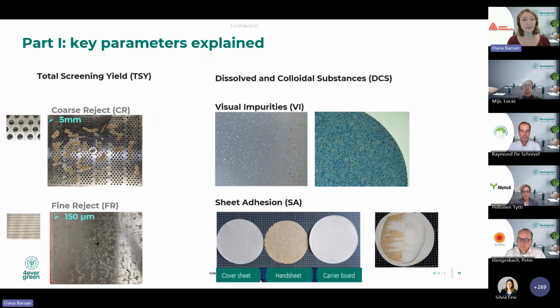And then there's a separate step called fine screening, where the smaller particles are separated, like fiber agglomerates that weren't properly disintegrated, adhesive particles, and so on. The accumulation of these 2 parameters lead to the calculation of the total screening yield. Another parameter is the dissolved colloidal substances, which essentially is the evaporation residue that remains in the water after the process is done.